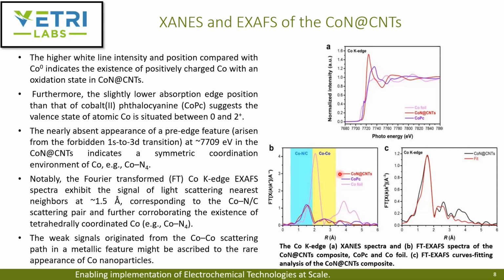And based on the EXAFS, they can see that the EXAFS spectra exhibited a signal at a scattering radius of about 1.5 Angstrom, corresponding to the Co-N scattering pair, and further giving the existence of cobalt coordinated with 4 nitrogen atoms. And the weak signals originating from the Co-Co scattering path in a metallic feature can be ascribed to the rare appearance of cobalt nanoparticles.